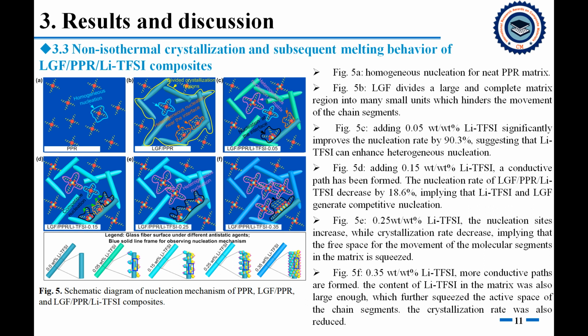Adding 0.15 weight%, a conductive path has been formed. The nucleation rate decreases, implying that organic salt and long glass fiber generate competitive nucleation. Continually increasing the organic salt, the nucleus size increases while the crystallization rate decreases, implying that the free space for movement of the molecular segments in the matrix is squeezed.